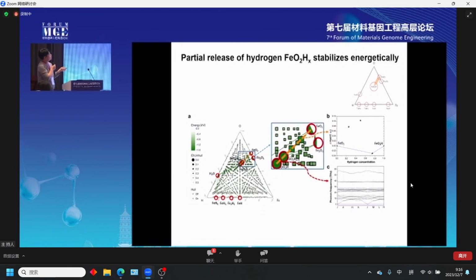And if you look very closely at this ternary phase diagram, what I calculated a long time ago, this was a very costly calculation. I did it like 7 or 8 years ago. So if you see this, this is iron, oxygen and hydrogen at 100 gigapascal. In the center, this is FeO2H, and here is FeO2. Along this line, there are many phases that can be stabilized energetically, or can be stabilized in terms of phonons, meaning a metastable form.